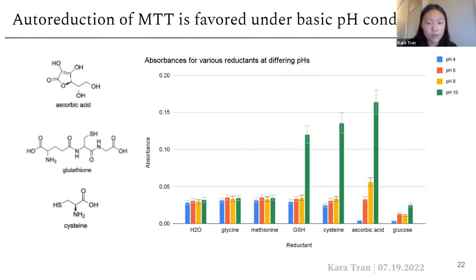To solve this issue in the future, these results indicate that we should either use a media with reduced levels of ascorbic acid, cysteine, and GSH when running the MTT assay, or simply use a higher concentration of cells to counter the autoreduction.